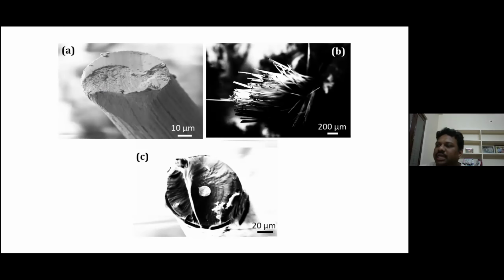So during this journey, initially Kaisen, a PhD student, started off this work. We were working on different varieties of fibers, like tungsten, silicon carbide, and titanium. All these fibers we investigated to see if they reinforce properly, though it's a big challenge because single grain growth itself is very complex. Once you introduce elements like tungsten or titanium, which have melting points higher than the peritectic temperature of the YBCO or REBCO itself, then the chances of getting a single grain are very minimal.